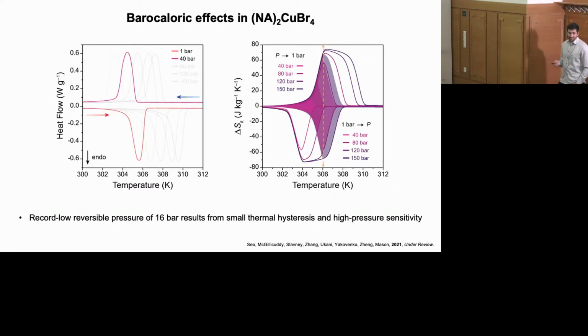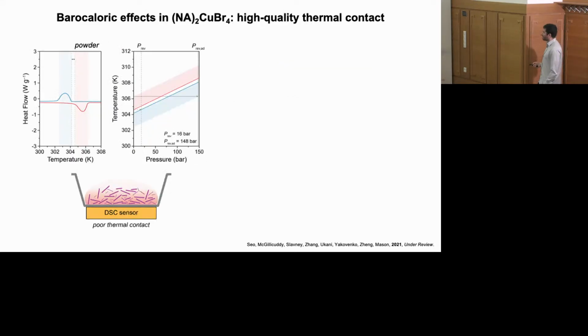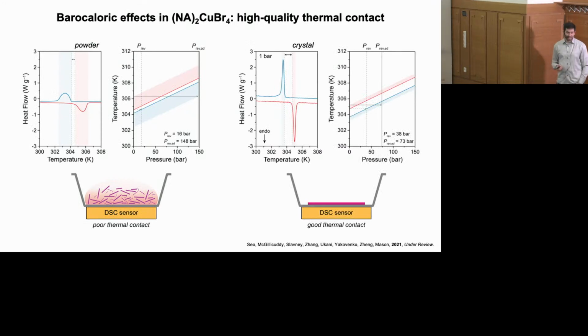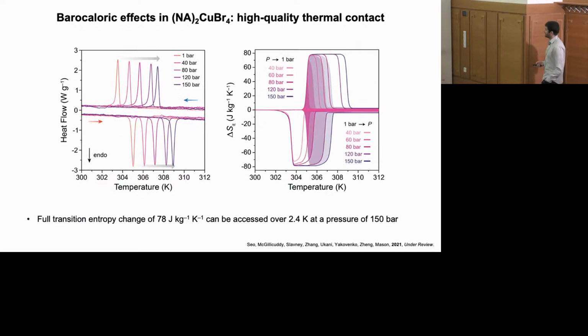And so we can do similar kinds of thermodynamic analyses to evaluate the magnitude of the reversible entropy change that you can induce, i.e. how much heat you can withdraw on a given cooling cycle by operating the phase transition reversibly. And we see similar kinds of effects as we move from a powder sample to a single crystal sample with high quality thermal contact. We get really sharp phase transition peaks. And so now we can drive phase transitions reversibly by swinging between just a pressure of 1 bar and 150 bar, so a relatively small change.